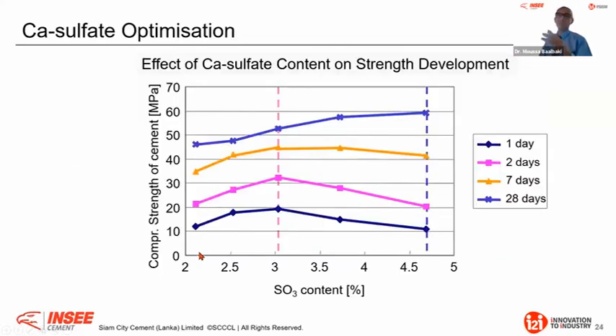Now, when I was discussing calcium sulfate optimization, when we optimize gypsum, this is very, very important. When you get a finished product, you cannot do this. But if you produce your own product, you can optimize the gypsum, because as I say, gypsum plays a very important role, not only in regulating the C3A, but also in regulating the dissolution rate, during the dormant period, of different species that need to grow in the solution and come topochemically to the surface of the cement grain to develop the hydrated product. Therefore, you can see here, for example, at different ages from 1 day to 28 days, these are the compressive strengths.